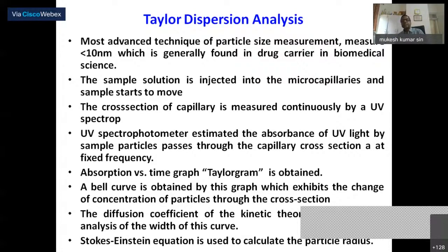The sample solution is injected into the micro capillaries and the sample starts to move. The cross-section of the capillary is measured continuously by ultraviolet spectroscopy. UV estimates the absorbance of UV light by a sample particle which passes through the capillary cross-section at a fixed frequency. Why is the fixed frequency used? If you change the frequency, you will not get precise results. So the frequency will remain constant, and as the particle size changes, absorbance will change. The absorption versus time graph that is called the Taylorogram is obtained by means of this technique.